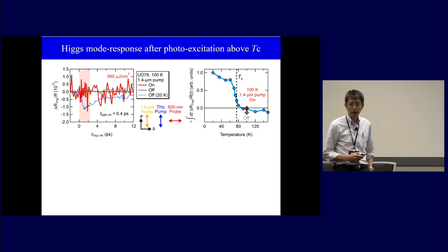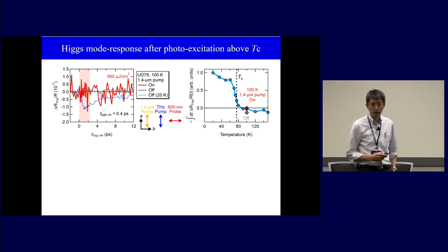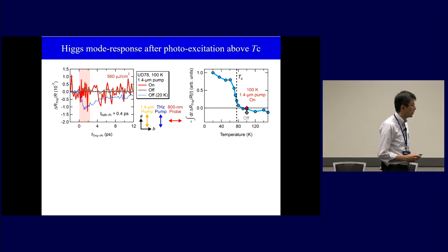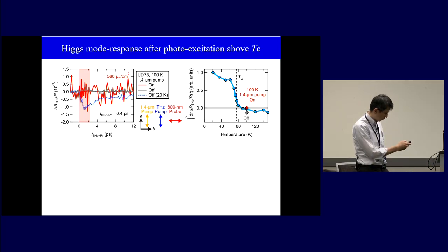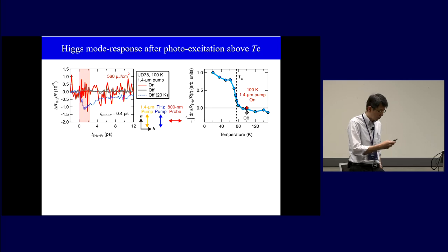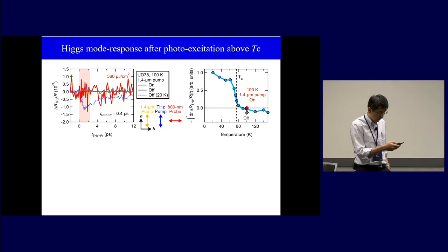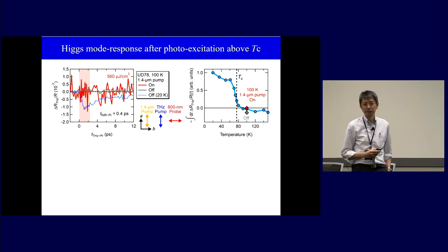Just one quick question. Of course, you observe, and we observe, that in the c-axis you have this enhancement in sigma 2 that tells you that there's a pole at zero frequency somehow. But also sigma 1 goes up, so there seem to be hot quasi-particles. Are these hot quasi-particles expected to be detrimental for this signature? Well, even if there are quasi-particles, we should see this signal in equilibrium, so I don't think it suppresses this nonlinear signal. We also tried this third harmonic generation along the c-axis that is coming from the Josephson plasma, as you showed. And we also see this signal in YBCO, but no Tc signal above Tc, for near infrared pump.